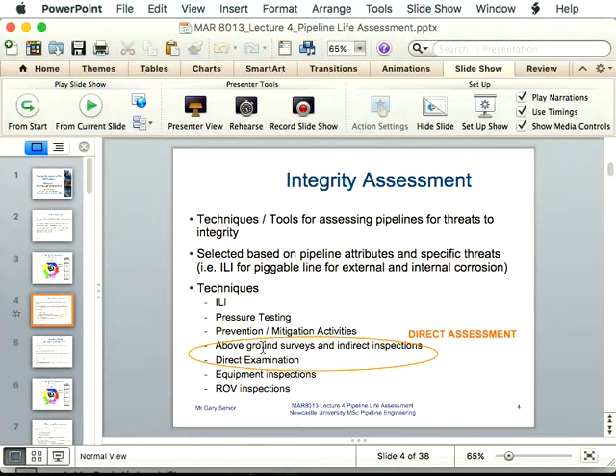And that does happen if you have what's called rogue material. So you're meant to have a yield of 450 megapascals, and you've got a wall thickness of 11.91 millimeters, for example. And all the steel mills provided all that, and you've put it in, and that's all good stuff. But the supplier ended up providing you some 7.1, not just 11.91. So most of it's 11.91, it's correct, but maybe he's got 20 pipes in there somewhere that are only 7.1. So once you start doing your nice pressure test, at some point you will go beyond the elastic limit, the yield point obviously of the material, and it will start globally plastically deforming and ballooning, literally. So it'll still be containing, but it'll be permanently deforming.